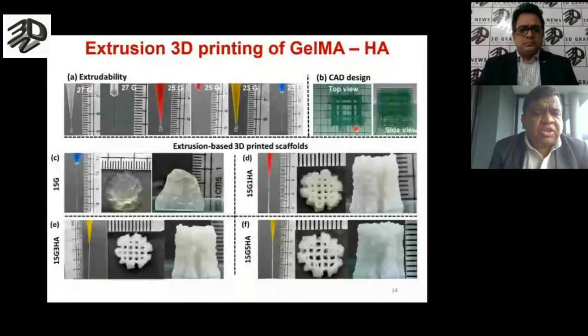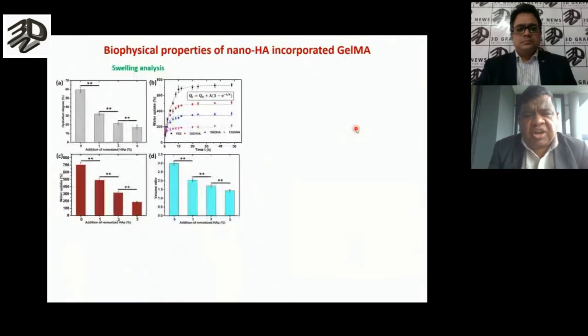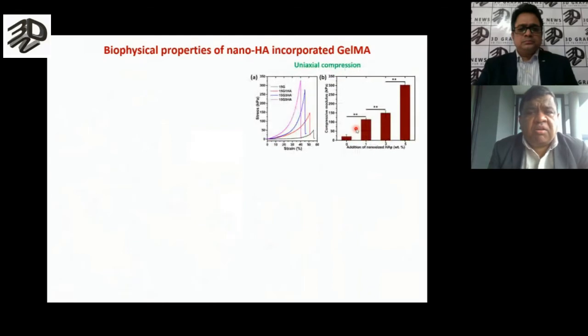We have done extrusion 3D printing of gelatin methacrylate nanohydroxyapatite. We are able to grow large structures. I'm going to show you how these structures were made. But before that, I want to show you some scientific results of this nanohydroxyapatite reinforced gelatin methacrylate. What you see is that their swelling analysis can be quantitatively assessed, and it shows very good swelling properties, and also their uniaxial compression properties.